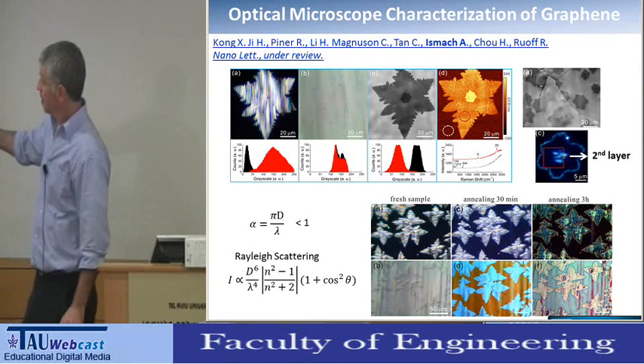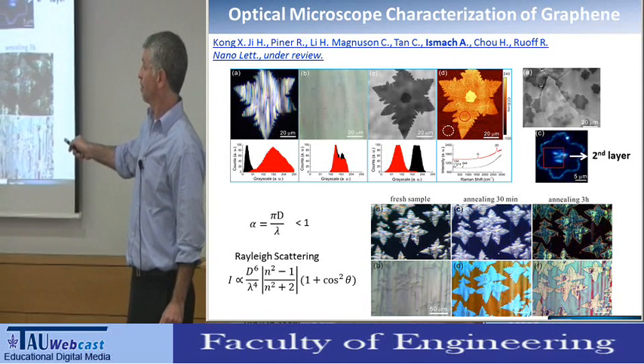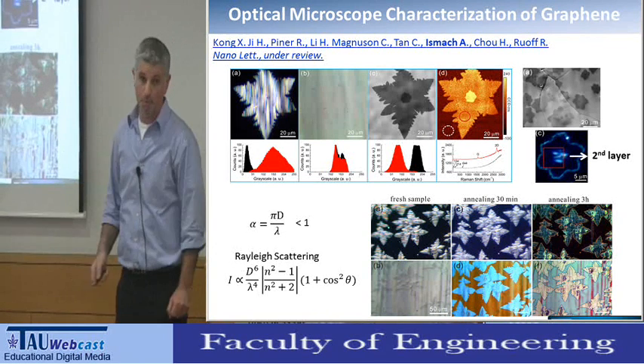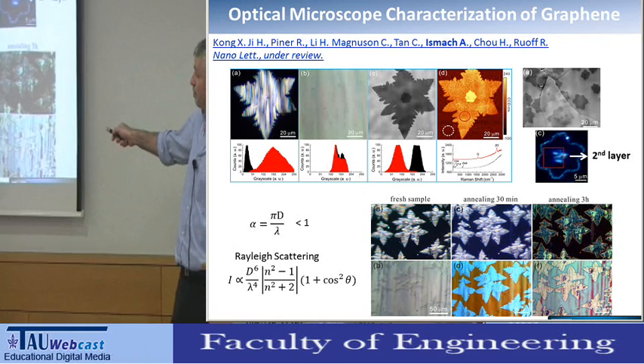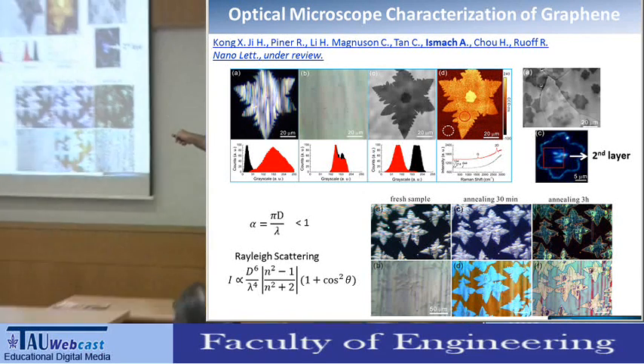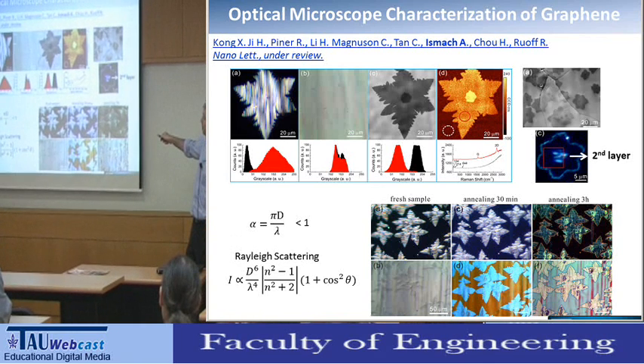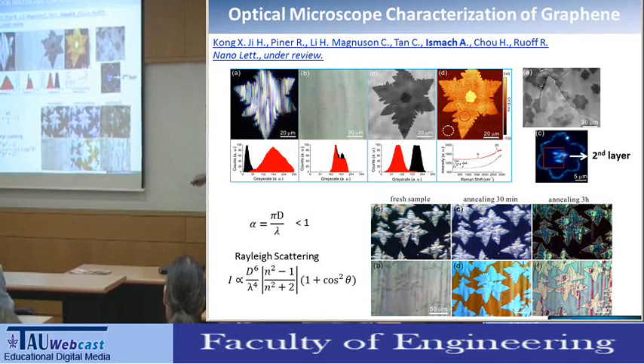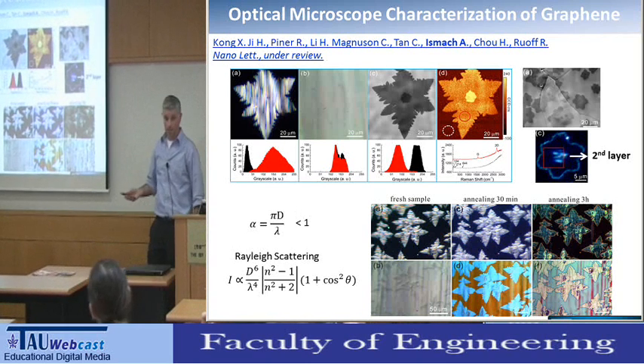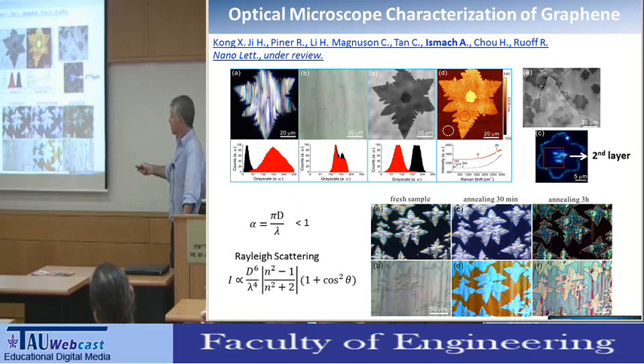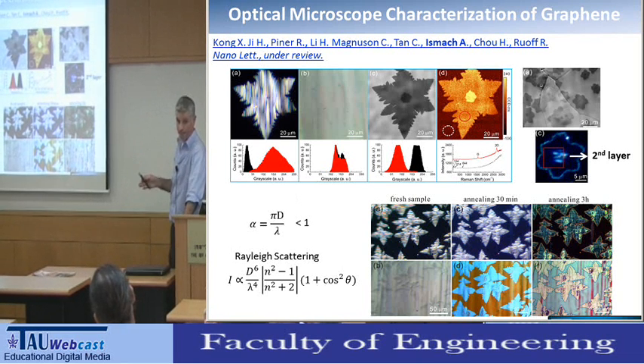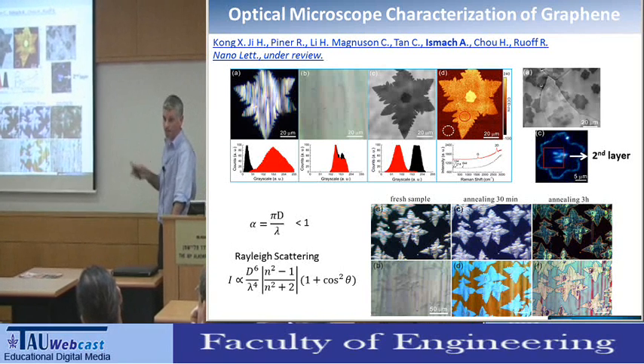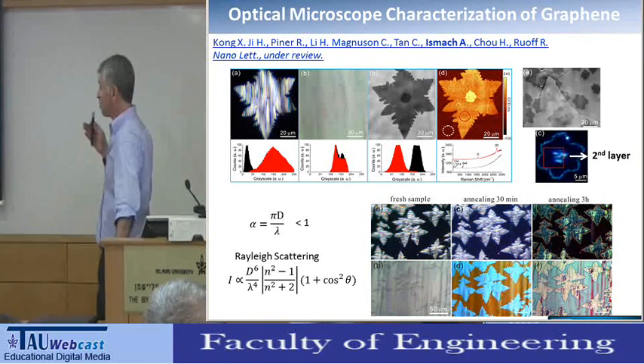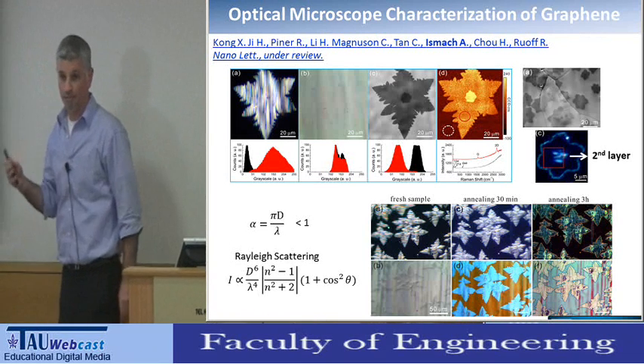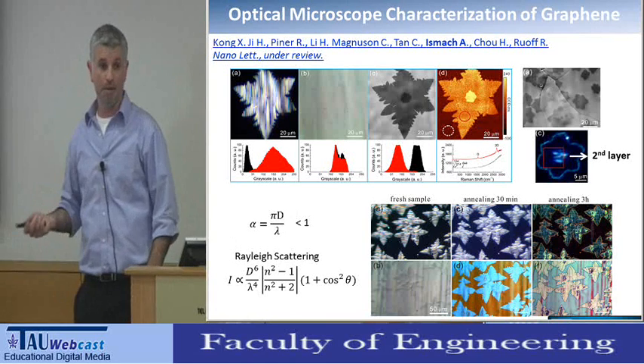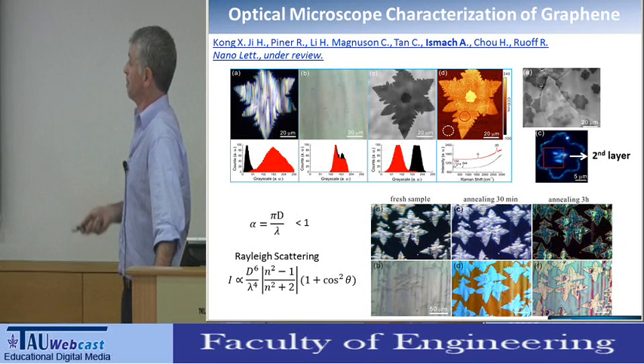Here you can see, so this is a submonolayer graphene that grew on a copper foil. This is just after growth. And here you can see the dark field image. This is the bright field image. This is the SEM. This is the Raman. And you can see that in the bright field image you can't detect any graphene. But in the dark field image, you don't see directly the graphene, but you see the facets of the copper that are underneath the graphene, and that are preserved due to the protection of the graphene. All the rest of the area is oxidized by exposure to air.